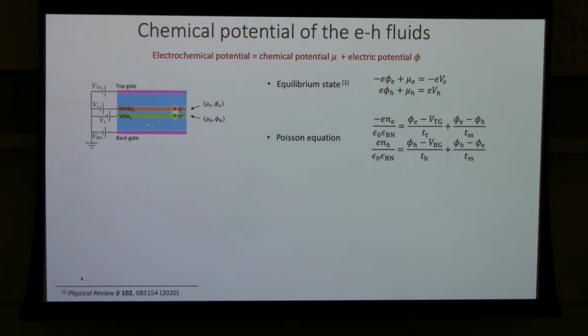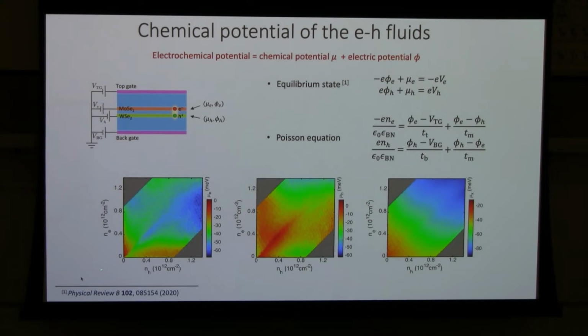But then if we also know the electron hole density, we can actually solve the Poisson equation to determine the electrical potential. So with the electrochemical potential controlled by the bias voltage and also the electrostatic potential, we can use this information to calculate the chemical potential of the electrons and holes as a function of electron hole density. This is the chemical potential for electrons and the chemical potential for holes as a function of electron density and hole density. And this is the chemical potential for mu_e plus mu_hole, which is the exciton chemical potential.